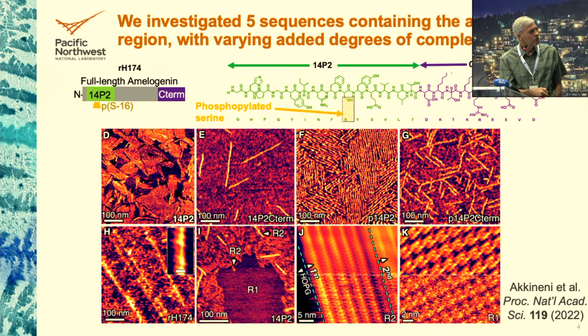So what did we find? Well, first of all, these assemble in solution into the cross beta sheet structure. All of them do. But that doesn't do us much good for studying nucleation because there is no technique for looking at nuclei on individual proteins in solution. However, AFM can do this quite effectively, and what we found is that these will assemble into the beta sheet ribbons on graphite. Now, it's not cross beta sheet, it's only half, because now the hydrophobic side doesn't need the other beta sheet to get away from water. It puts that hydrophobic side down on graphite. But the side that mineralizes, that's exposed in the cross beta sheet, is the thing that's exposed to the solution.